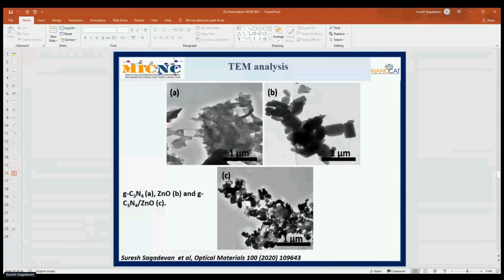And next, we studied the surface morphology of the three prepared samples. A is graphitic carbon nitride, B is zinc oxide, and C is the composite. You can clearly see from the TEM image that graphitic carbon nitride has a sheet-like structure, exhibiting morphology similar to two-dimensional agglomerated laminar sheets with rolled edges, but the sheets are folded and exfoliated in the sheet arrangement.